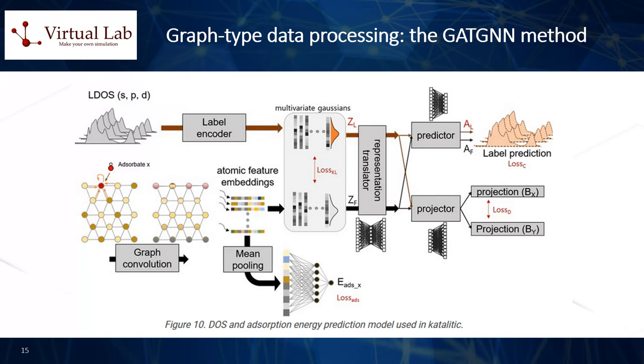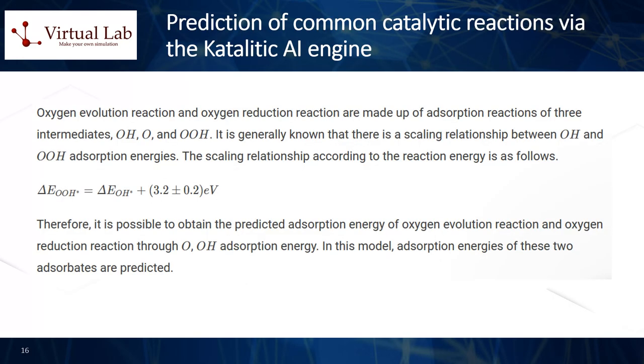The viewer is referred to the Katalitic official documentation at katalitic.io for further technical information on the functioning of the AI engine. The oxygen evolution and the oxygen reduction reactions in catalysis are made up of adsorption reactions of three intermediate states: individual oxygen, OH atoms, and OOH. There is a well-known scaling relationship between the OH and OOH adsorption energies, allowing the predicted adsorption energies of the oxygen evolution reaction and oxygen reduction reaction to be obtained through the individual O and OH adsorption energies, which are predicted as a starting point under this AI model.